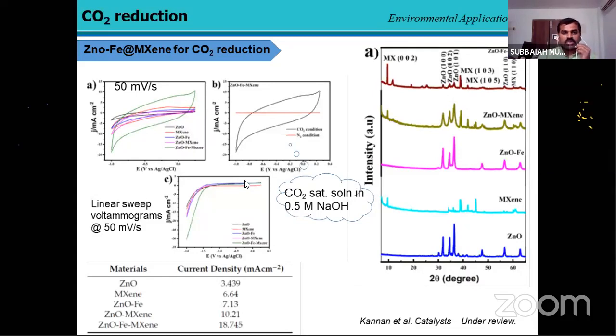From the cyclic voltammetry, they found a current density of 18.745, which is much higher than the other materials developed for this study. Then they utilized carbon dioxide saturated solution in 0.5 molar sodium hydroxide.